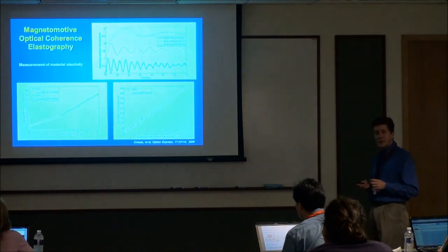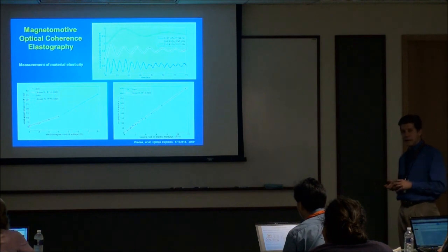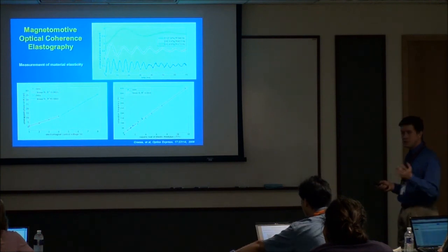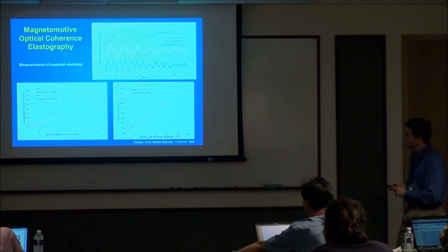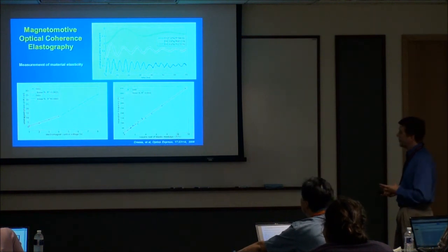So we're able to use these as optical rheology agents to characterize the mechanical properties of the tissue or microenvironment. This was a study done using gels at different stiffness. And we can see that as the stiffness of the gel got higher, going from green to red to blue, the oscillation frequency got higher and higher as well. And this fit quite linearly to this plot of relaxation frequency versus the square root of the elastic modulus. So very predictable.